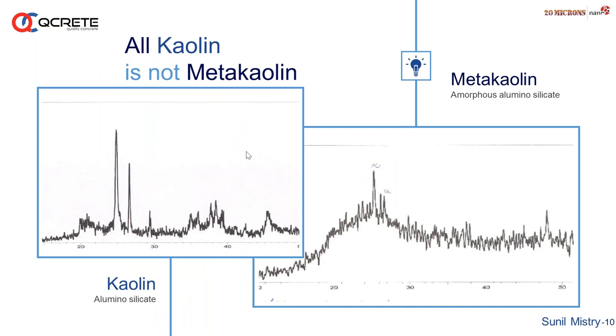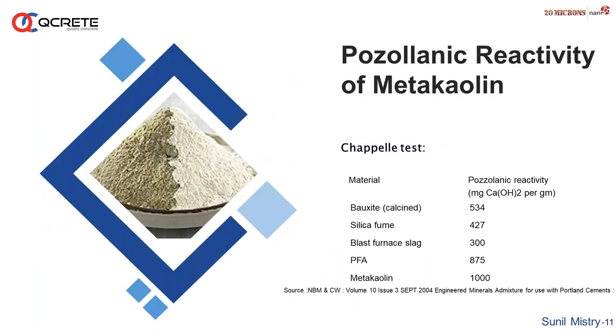So I'm just explaining this also. All kaolin is not metakaolin. I'll explain in a few lines the difference between kaolin and metakaolin. You can see on the left-hand side the screen showing an X-ray diffraction pattern of the untreated kaolin, though it is a refined one, and it shows some crystalline peaks, whereas the amorphous material doesn't have a crystalline peak. So this is the difference between kaolin and metakaolin.